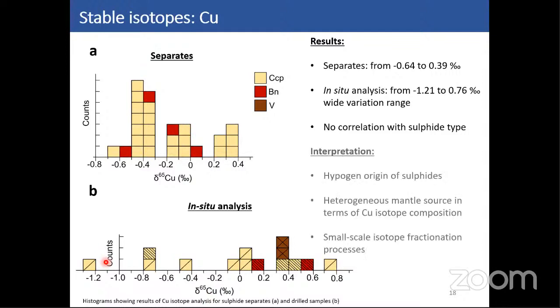Several points can be made from these results. The first one is the presence of hypogene sulfides, considering the variation range of sulfide separates, which is comprised between -1 and 1 per mil. Second point is that despite the fact that the variation range of separates is kind of small, there is still some variation, which suggests that the metal source is, in addition to being chemically heterogeneous, as we've seen with the variation in terms of chalcopyrite and bornite proportions in the different sulfide layers, obviously heterogeneous in terms of copper isotope composition. And the last point, when we observe the in situ samples, is that we are obviously in presence of small-scale isotope fractionation processes.